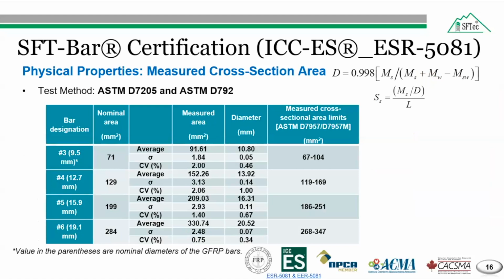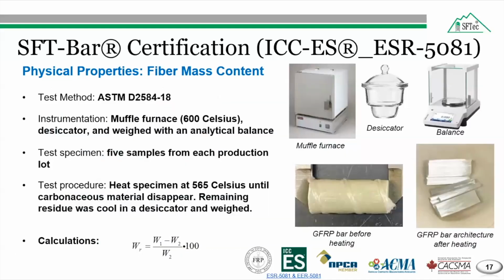So for the tested helical wrap glass fiber reinforced polymer bars, the averaged measured cross-sectional area was greater than the nominal cross-sectional area, as shown in this table. And it was within the required cross-sectional area according to the AC 454 acceptance criteria, which is based on table number 3 of ASTM D7957. The AC 454 acceptance criteria suggest that the requirements should be met according to ASTM D7957.